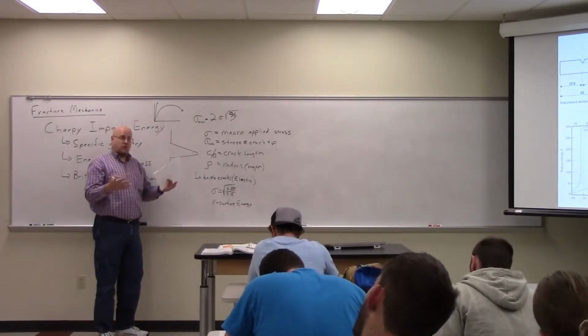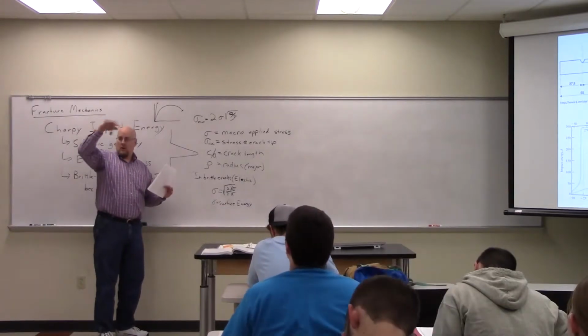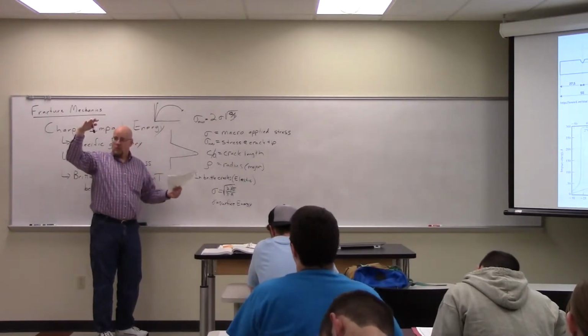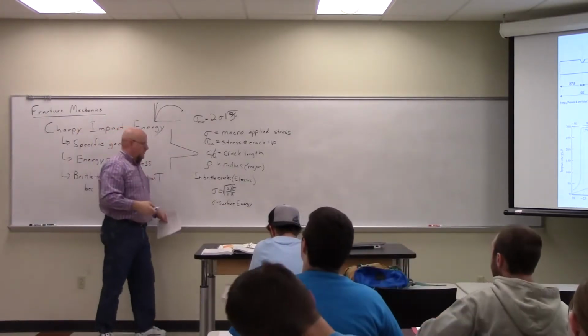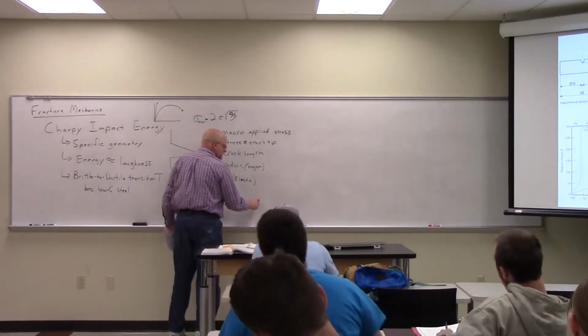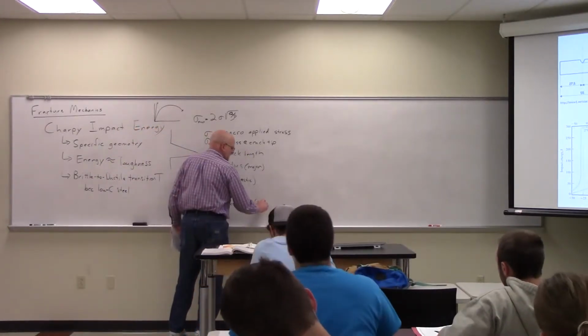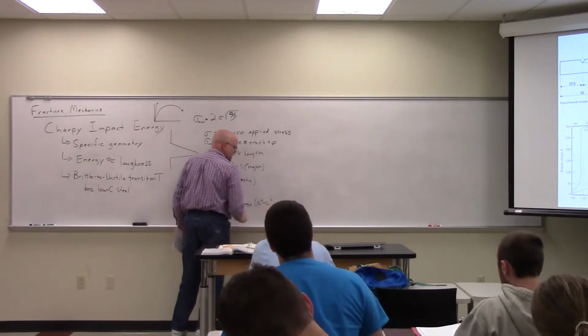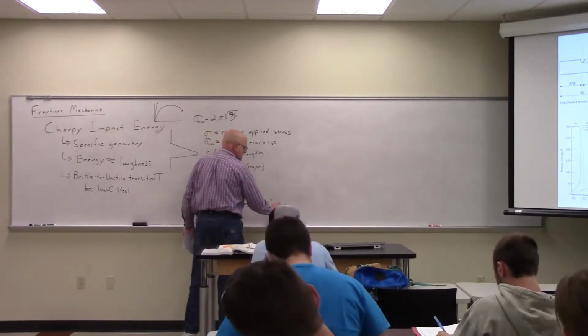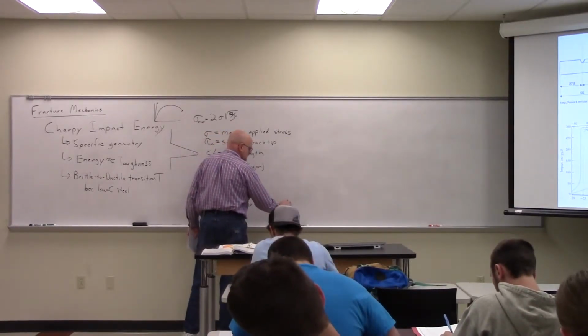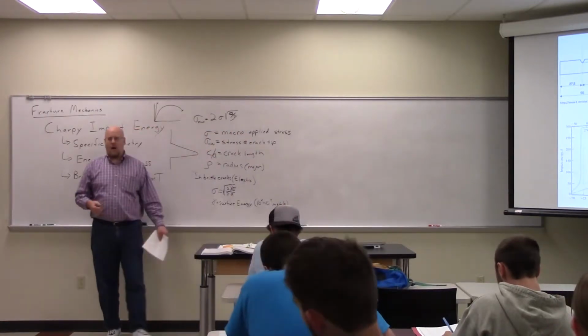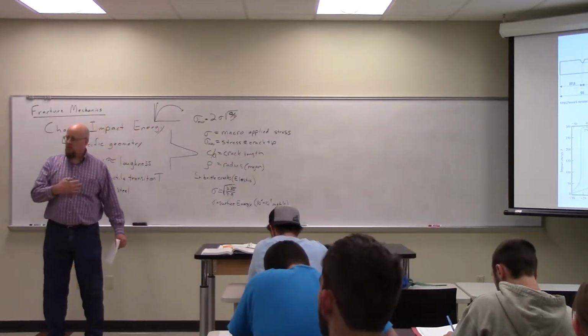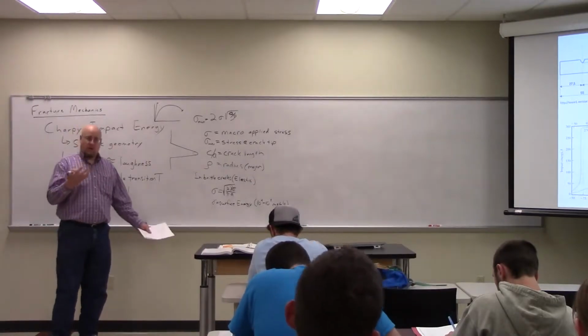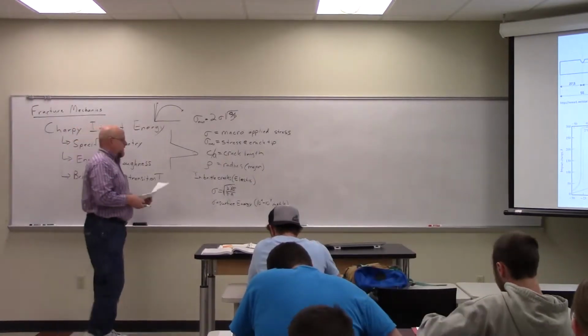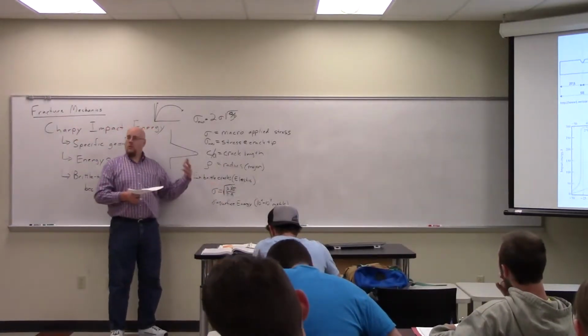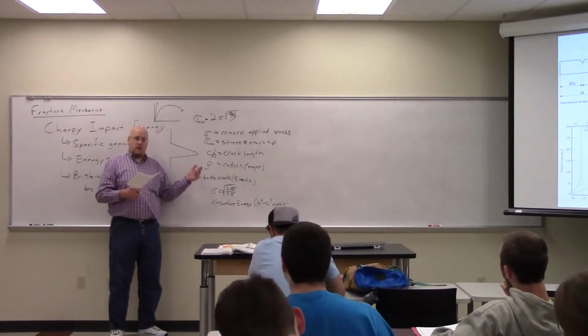And there's an energy associated with having a surface, because it doesn't want to be a surface. It wants to be made into itself. So the surface energy is on the order of 10 to the second to 10 to the fourth for most metals. For a polymer, it'd be less than 100, so below that range. That's why it's easier to crack a plastic than it is to crack a metal, even a brittle metal.